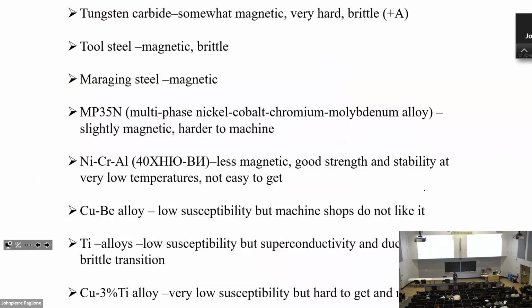Here is a list of materials that you can use to build this piston cylinder cell. I'll mention a few. The most famous is tungsten carbide. It's very hard, so very good for high pressure, but also very hard to machine. And it's somewhat magnetic. If you have extremely pure tungsten carbide, it will not be magnetic, but you don't get that. Industrial tungsten carbide typically is mixed with some cobalt or some iron, and so it's slightly magnetic. If you don't want this, you can use beryllium copper, which is also very good. However, typically you have 2% of beryllium in there. The machine shop will not like this. At least our machine shop refused to work on this. But it has very low susceptibility. Somewhere here you have a nickel chromium aluminum.